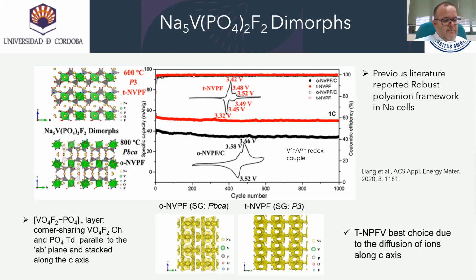The three-dimensional bond valence sum mapping suggested the diffusion pathway in orthorhombic NVPF is discontinuous along the B axis. Therefore, the sodium ions are more likely to diffuse along the AC plane. However, for trigonal NVPF, the three-dimensional bond valence mapping shows that the sodium ions prefer to diffuse along the c axis. Due to the differences in the stacking of the AB chains in these orthorhombic and trigonal phases, the electrochemical properties differ, the trigonal NVPF being the best choice due to the diffusion of ions along the c axis.